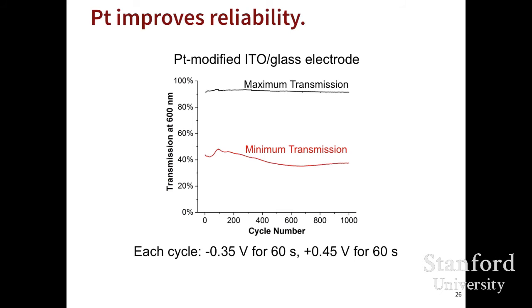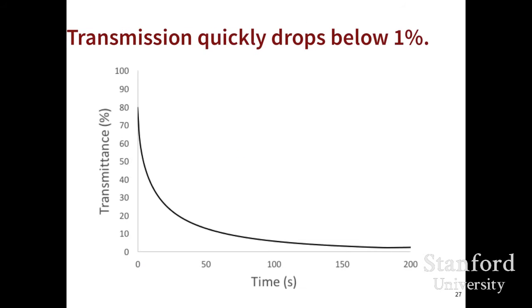Here we're cycling between 90 and 40% transmission. We could go deeper. We're just using a less aggressive cycling, and we're just doing a short switch there to do 1,000 cycles relatively quickly. This next slide shows just how low the transmission can go. You see here that after a few minutes, the transmission is well below 1%.